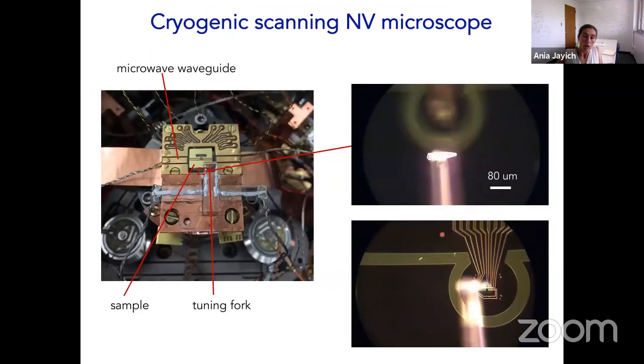Okay, and another technical challenge that we overcame a couple years ago, but just to show here what we do, is we have incorporated these diamond scanning probes into a 4 Kelvin cryostat to be able to study condensed matter systems at low temperature. Of course, one of the nice things about the NV is it operates at room temperature, but oftentimes for condensed matter systems, some of the interesting physics happens at lower temperature. And so to be able to study those systems, we've incorporated this into a 4 Kelvin closed cycle cryostat. This just shows some pictures of what it looks like.